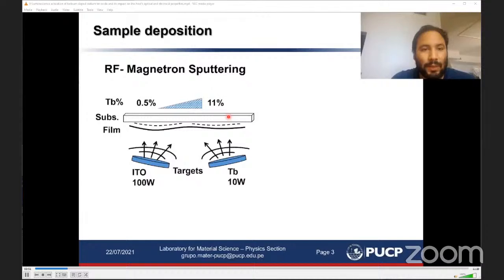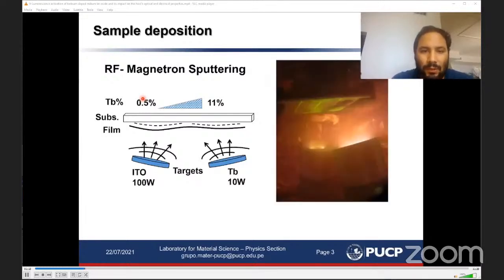We have grown our samples by radio frequency magnetron sputtering in a way that we are able to obtain samples with different terbium concentrations in a single deposition process. Additionally, we realized by experimentation that in order to activate the terbium-related luminescence by post-deposition thermal treatments, it was necessary to cool down the substrates during the deposition process. We performed this using a closed-cycle cooling system and put the temperature of the substrate down to 10 degrees Celsius.